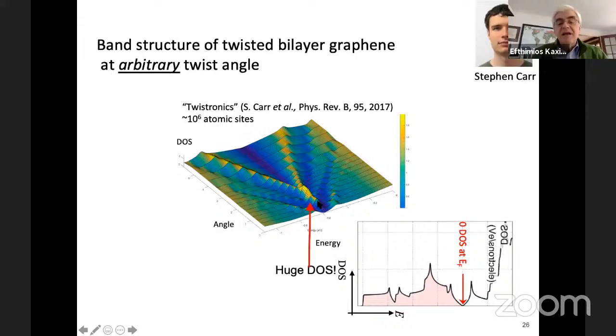And that's what's extremely important and extremely useful. If you have a huge density of states near the Fermi level, it means that you can produce very interesting behavior by supplying a few electrons near the Fermi level, which is easy to do, and explore the behavior of this large number of density of states electrons.